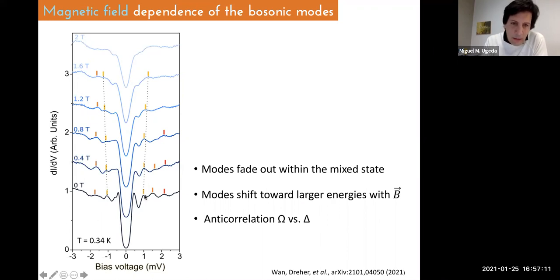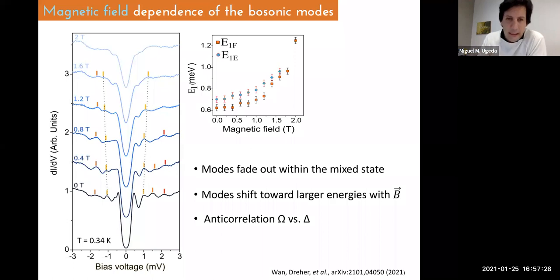But there is something really interesting: these peaks are not constant with the magnetic field, but also move. So here I show you this line and this line that you see that they open with the increasing magnetic field. And actually, this is the evolution of these peaks with the magnetic field.